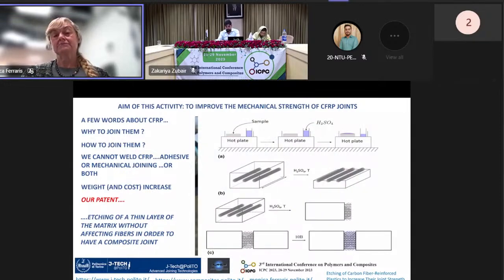I'll show you a quick drawing of how we work. We take the sample, the CFRP, and then there is an acidic etching, for instance by sulfuric acid. The aim is to expose the fibers without destroying them. If you do that on the other side, you can expose fibers on both sides, then infiltrate your adhesive, and you end up with a composite joint.